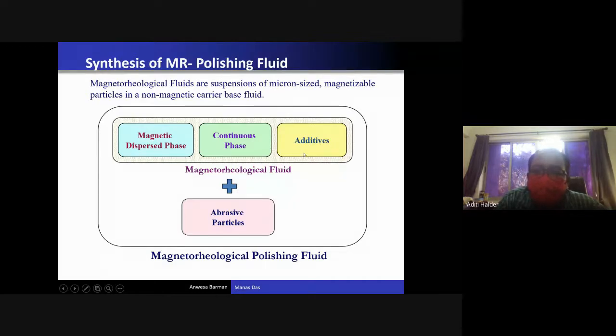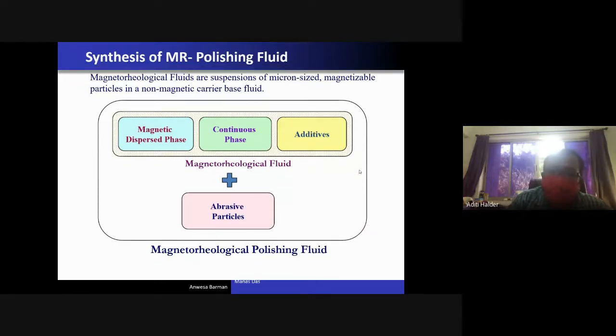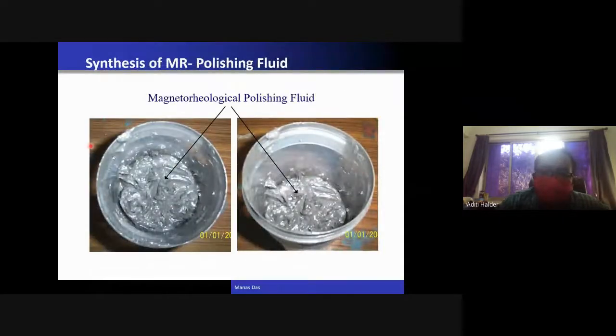But if you use more volume percent of these additives, what happens? Because of the higher thickness of this layer of surfactants, the magnetic field will be reduced. So they will be less magnetized in that case. Now, after mixing all these things, if you mix in the abrasive particles, this MR fluid will become magnetorheological polishing fluid. Now coming to this media, you can see this kind of thick media which is generated when you are using MR polishing fluid.